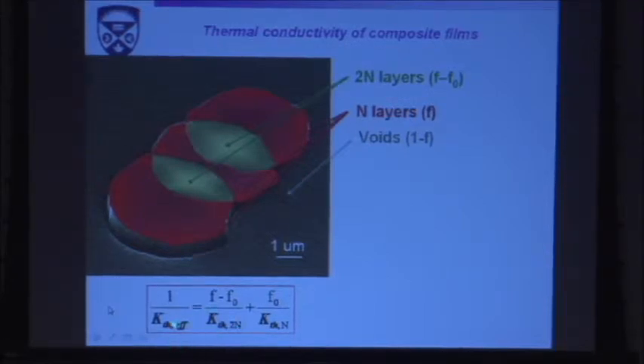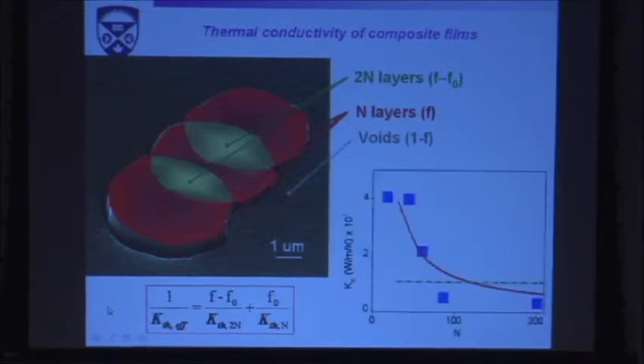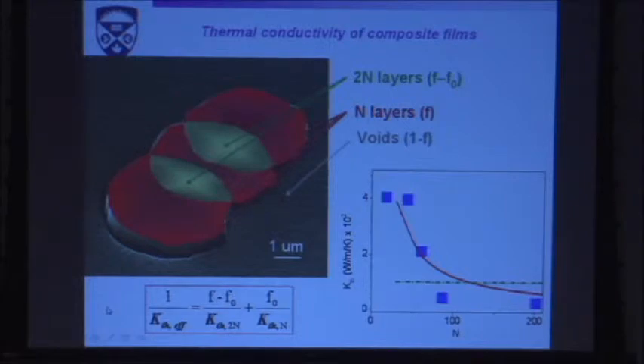So if you use a formula like this, the actual thermal conductivity of your film is a parallel of the area with a thickness of 2n layers, so an overlap, and the other component of the parallel is the area where you have just one layer, one flake. You get a pretty nice relationship for the thermal conductivity using the Klemens formula, and that explains the decrease of your thermal conductivity.